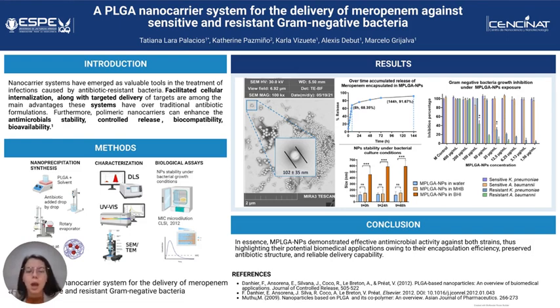In essence, meropenem PLGA nanoparticles demonstrate effective antimicrobial activity against both strains, thus highlighting their potential biomedical application owing to their encapsulation efficiency, preserved antibiotic structure, and reliable delivery capability. However, future investigations are necessary to explore the effect of particle size, surface charge, and material composition of these nanoparticles to assess the antibacterial activity.